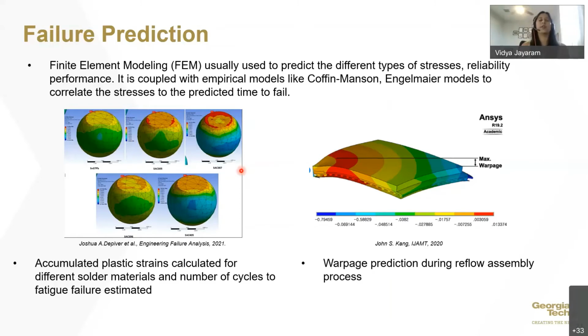For example, for thermal cycling reliability, where you subject the samples to cycles of high and low temperatures, it can predict how many cycles to failure based on the input parameters. So it's a very effective tool in predicting what the failure might look like. But before you even go to this sort of predictive modeling, it's important to understand what kind of failure modes you would expect so that you can model accordingly. Since there's no model without existing empirical data and your input based on the failure mode that you expect.